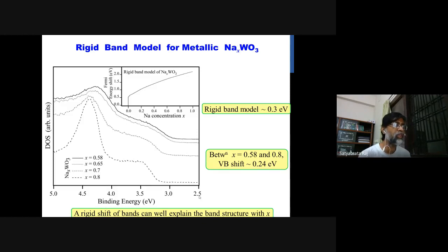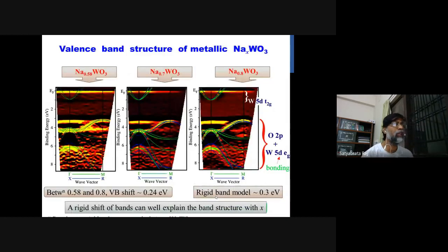So our conclusion is that a rigid band shift can well explain the band structure with respect to sodium doping purely in the metallic region. This is one issue which we concluded: the rigid shift of the band is applicable. Now we have mapped the band structure and overlapped it with the band calculations, and this rigid shift can well explain those things.